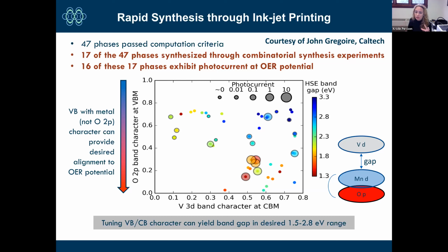They're not all as good. You can see from this graph here, where the radius of the circle is a sign of how much photocurrent we're getting. So bigger circles, better. And that really did correlate. So even though 16 out of 17 had some response, some were better than others.